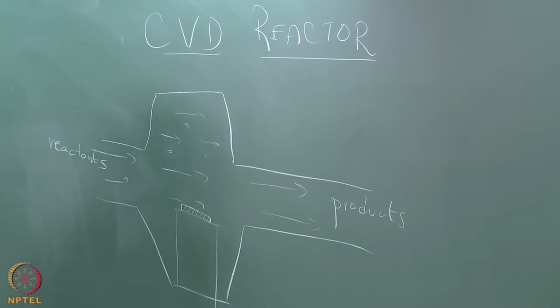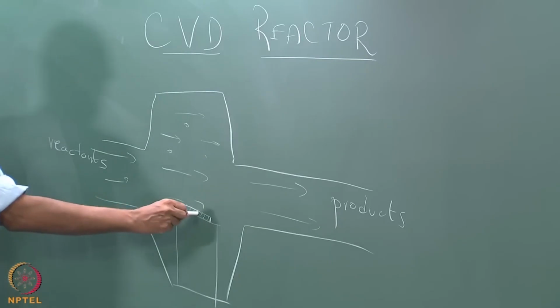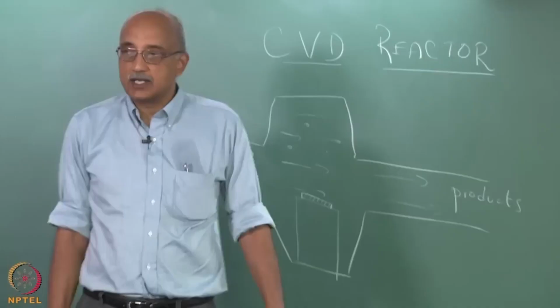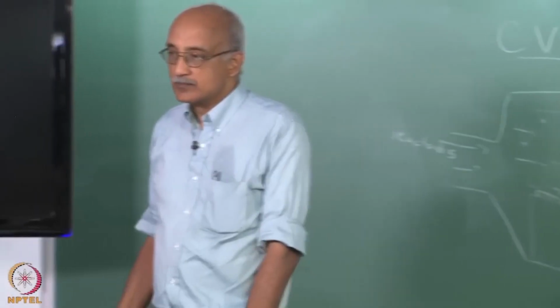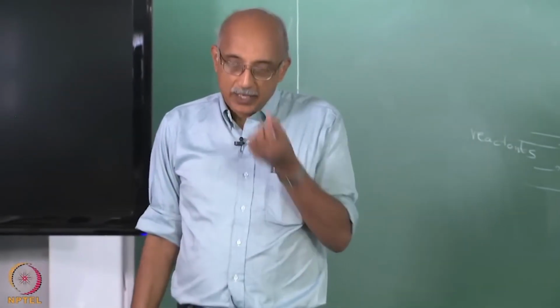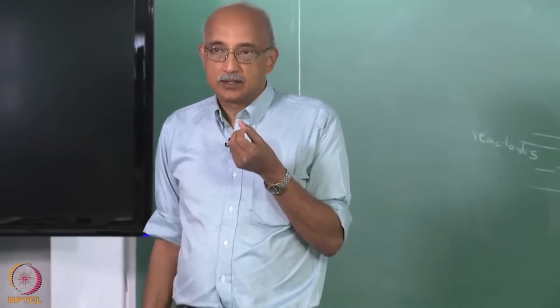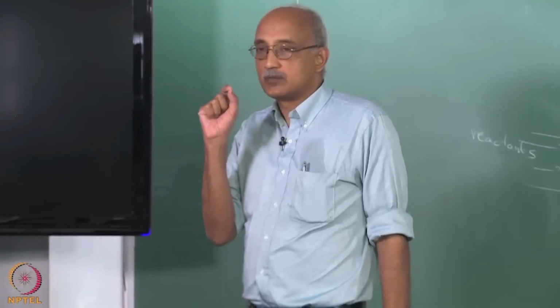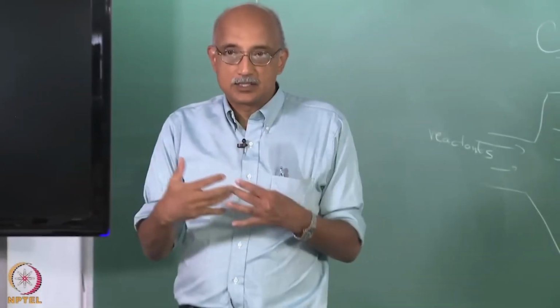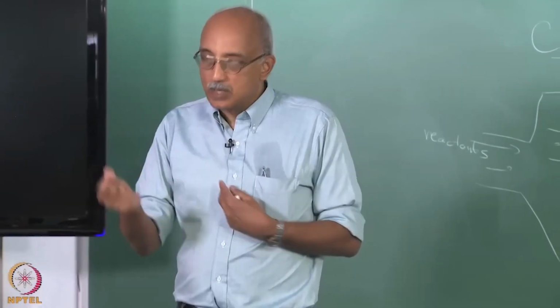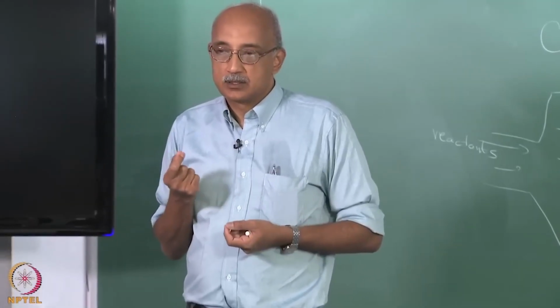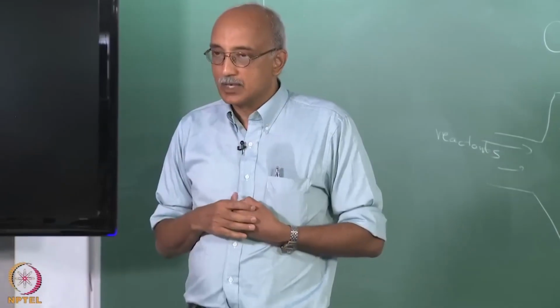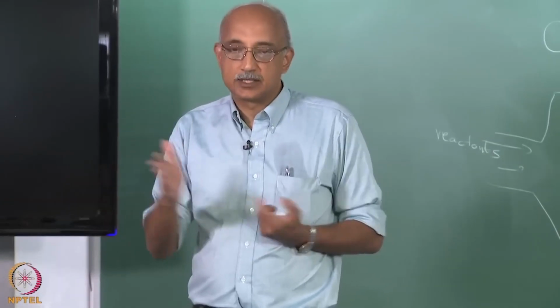Now, in essence, that is actually very different from what is known as a chemical vapor synthesis reactor. In a CVD reactor, you want the condensation to only happen here. In what is known as a CVS reactor, or a chemical vapor synthesis reactor, you actually use the reactor to make nanoparticles, and the way you do that is by promoting homogeneous nucleation and getting these very, very fine particles to form in the gas phase, and then providing a mechanism for them to agglomerate and form larger particles which can grow to the nanometer size, and then you suppress it. You essentially freeze it at that point.